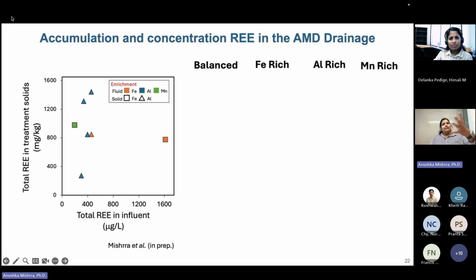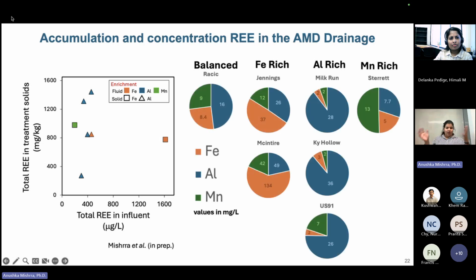So this came from the idea that now that we have such high concentrations of different elements, can we actually group them into categories of enriched solids? And so of the 7-8 sites that we have studied, we've tried to group them based on the influent, like the fluids. And you can see that there are more sites over here in our groups that are aluminum rich, meaning more concentrations of aluminum is present in them. And then there are some sites that have more concentrations of iron present in them. And there's one site that we definitely could get samples from that had more amount of manganese present in them.